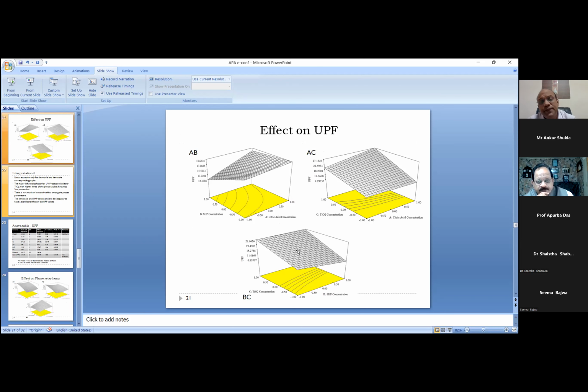Now coming to UPF, here in fact you find a linear equation. Here the quadratic equation didn't properly fit to the model. And here if I just summarize, I'd probably say that the TiO2 concentration is the lone contributing factor in terms of UPF, and that you can see here when you're increasing the TiO2 concentration, there is a significant increase in the